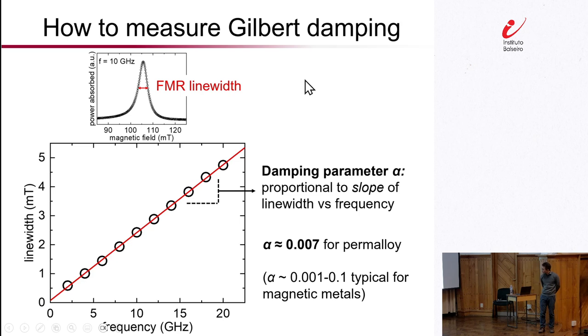So at least to me it's more straightforward to view line width being proportional to frequency because, something I haven't mentioned is, just like mechanical friction in the simplest sense, magnetic damping, or Gilbert damping here, is a viscous process. In other words, this is a process where you would see more dissipation the faster the dynamics. So my understanding is that's why we would naturally see line width scaling linearly with frequency.